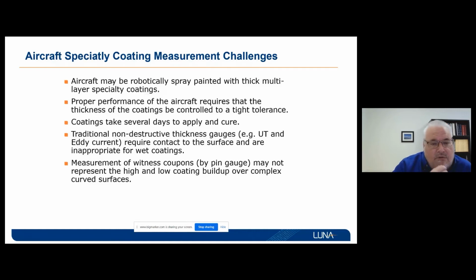Another advantage too is that we've further developed the method, I don't have this here, to essentially use electromagnetic modeling, which allows you to determine the thickness of a single layer without calibration. So essentially you can take it up to any coating and determine what the thickness of that coating is, even without a witness coupon.